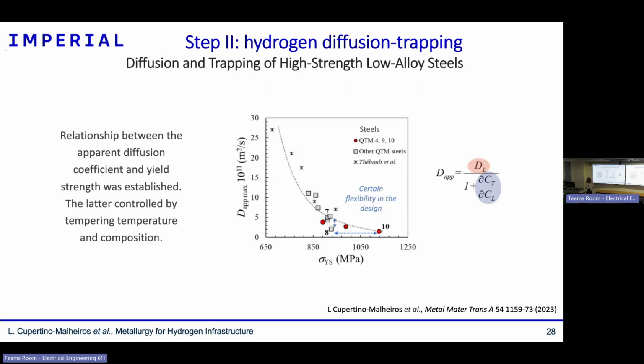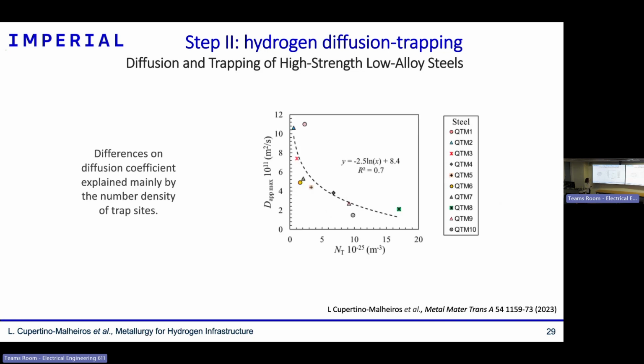One is how many of these structural features there are in your structure. That's usually called NT, the number density of trapping sites. And the second one is how strongly hydrogen is attracted to these features, that is the energy of attraction, the binding energy. So for this research specifically, I have seen that for these steels it is not the binding energy, how strongly hydrogen is attracted to the defects, that changes and justifies the differences in hydrogen diffusion kinetics, but the number of these trapping sites.